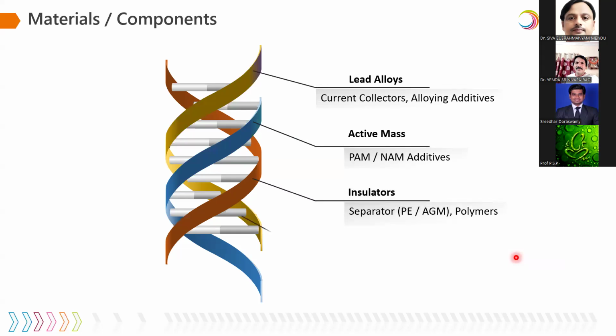Now, for any energy storage device, normally a positive electrode, a negative electrode, and separators separating those electrodes are the critical elements, along with the electrolyte having ionic conductivity. Similarly here in the lead acid battery, as current collectors for positive or negative we have lead alloys. There is a primary metal, and also alloying additives. And the active material, which is lead oxide or lead suboxide, which we have seen in the electrochemical reactions in the previous slides. So we term it positive active material, negative active material, and the additives which influence the performance of those electrodes, and insulators, which are the separators.